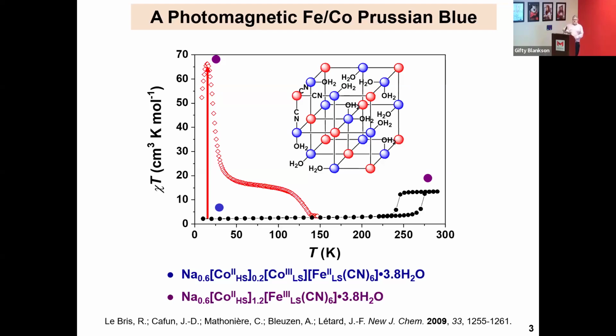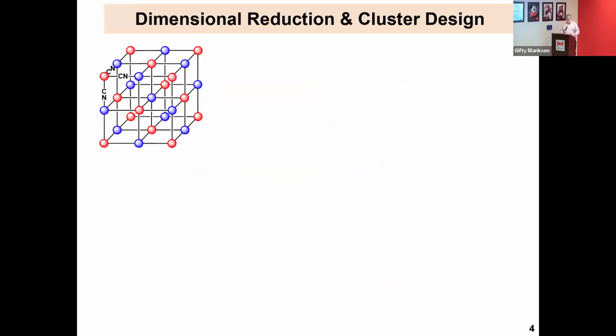And then as you go up further again, you recover your electron transfer again, and you get into this regime up here. And depending on if you cool it or heat it, you get something called thermal hysteresis. That's that sigma-shaped thing up at high temperature. And the width of that is indicative of long-range cooperativity in terms of this breathing of the material. And if the bonds are getting bigger, things have to move, takes time. And if it shrinks, it does it as well, takes time and energy.